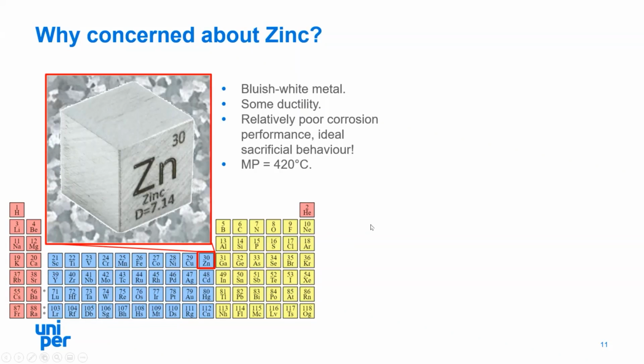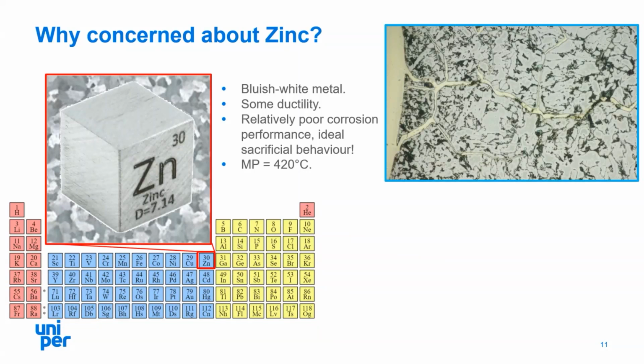But perhaps its position in the periodic table gives a few clues as to why there might be more concerns about it than purely the behaviour which is described there. Next door to the right, you see gallium. Certainly not a material that you would like to take onto an aeroplane that's got an aluminium substructure, due to the risk of liquid metal embrittlement. And to the left, we have copper, which has been seen on more than one occasion on power plant, where the melting of copper deposits on the internal surface of the component has led to liquid metal embrittlement.